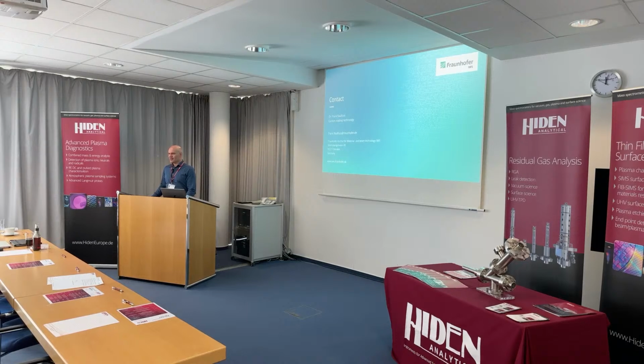The grinding is done in-house here? No, we do it by some adhesive tape, only cleaning up afterwards. This is working fine. We're also using a mechanical shutter system, so it's just a shutter of metal sheet, and then we can just turn it into the plasma plume. So when we know, okay, we would like to make some initial evaporation process when we start, then it's not necessary to make a tuning process or something like that. So we use the shutter, and then after several minutes, let's say 30 minutes, we open the shutter back. And so we prevent the orifice from getting covered by the carbon.